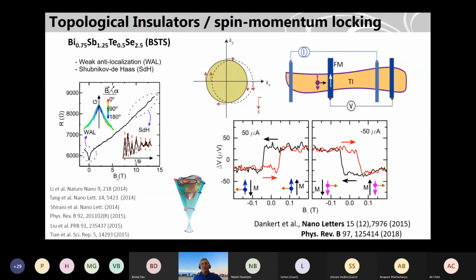But if you measure bulk samples, you see very nice oscillations. This is the oscillation you see here after subtracting a background. This is called Shubnikov-de Haas oscillations. From there, we can find the mobility of the sample and also the carrier density. With this, we can say where we actually are in the gap, so how much below the conduction band we are. I hope I answered the question.